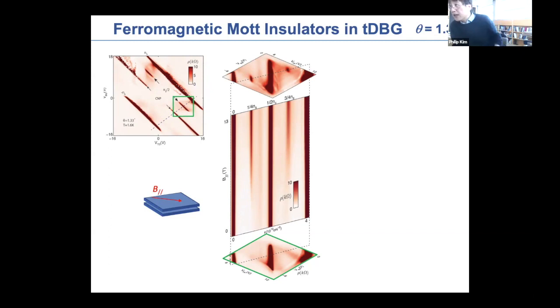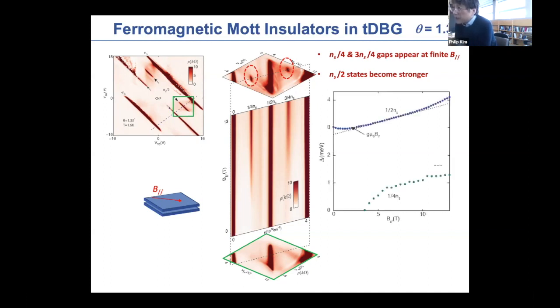But in this particular case, first the gap is stabilized only with this displacement field. And the gap is actually strengthened by the in-plane magnetic field, which increases the Zeeman effect, the Zeeman gaps. So from this, we start to contemplate that this correlated insulating gap that we have is likely the spin polarized gap. In other words, it is basically a spin polarized band or ferromagnetic ordering that happens due to the correlations that we have. So that's the one thing that we start to see in this type of sample.